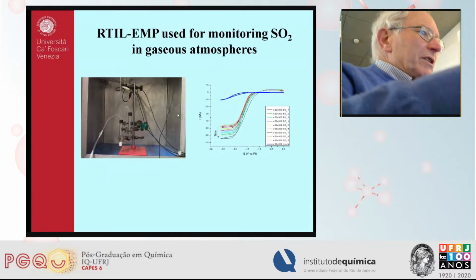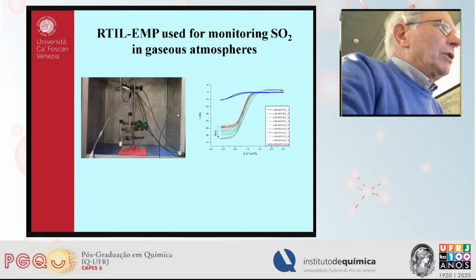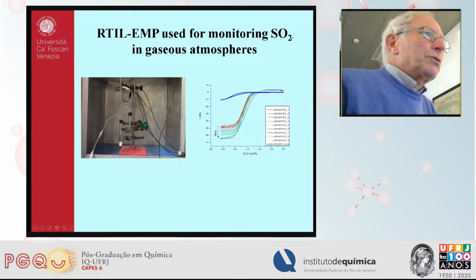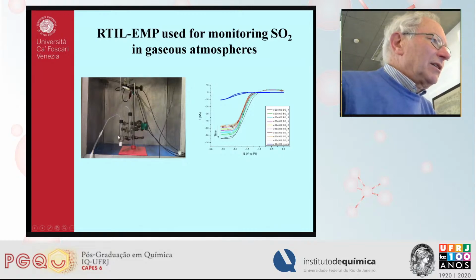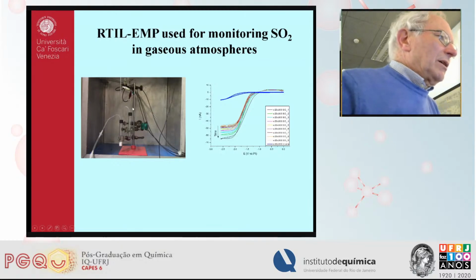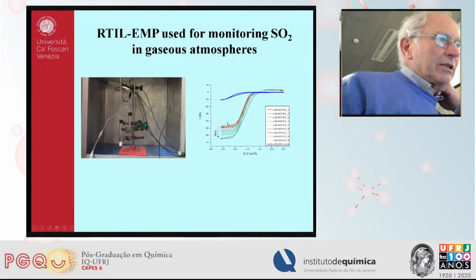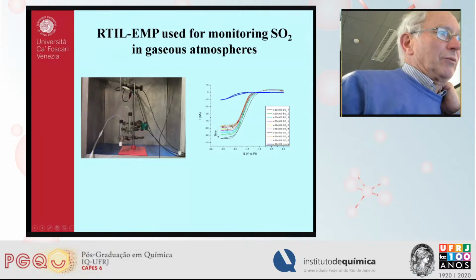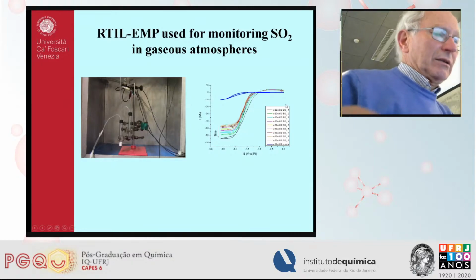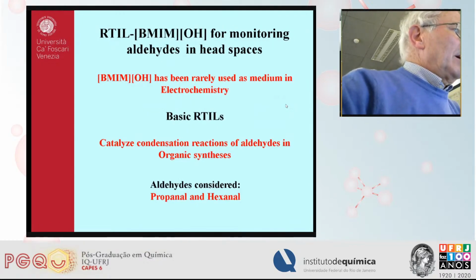So the same probe could be used, for instance, by changing the room temperature ionic liquid, for other gaseous species, for instance, for SO2. And these are a series of measurements performed in an atmosphere of SO2 created by developing SO2 from sodium sulfite and transferring it in the cell, in this container in which we put our microprobe. As you can see here, the limiting current of the responses increases with time, which means the higher the concentration of SO2 in this container, the higher the limiting current of the wave.